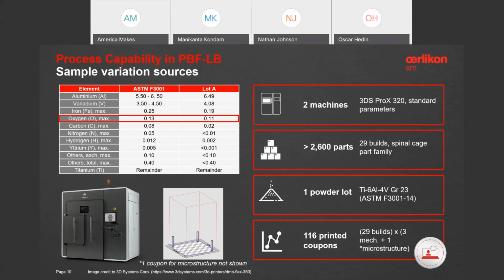A total of 116 coupons were printed across 29 builds. As you can see on the bottom left corner, that's our build volume. We use 4 coupons on 4 corners of the build plate, and we test 3 of them for mechanical testing and 1 for microstructural testing. A grand total of 116 coupons were printed and analyzed in the study. The microstructural coupon is not shown in this picture since it's IP of the customer.